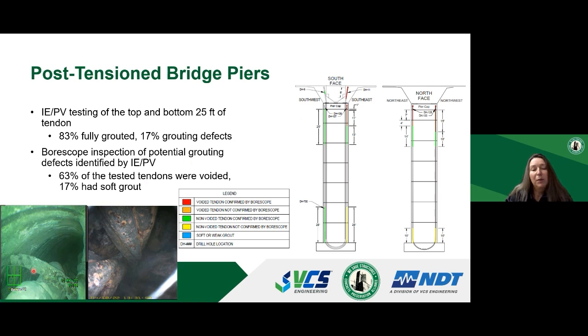Based on impact echo testing results, the majority of the borescope openings are located at defect locations, and we do some openings in fully grouted ducts as well for verification. So when the results are combined at the end of the project, we produce drawings that you see on the right side of the slide, where the tested tendon sections are color-coded based on impact echo and borescope results. The tendons that are colored in green indicate that impact echo testing showed that they were fully grouted, and this was confirmed with a borescope.